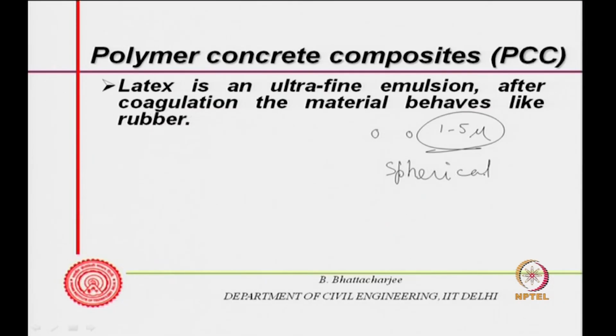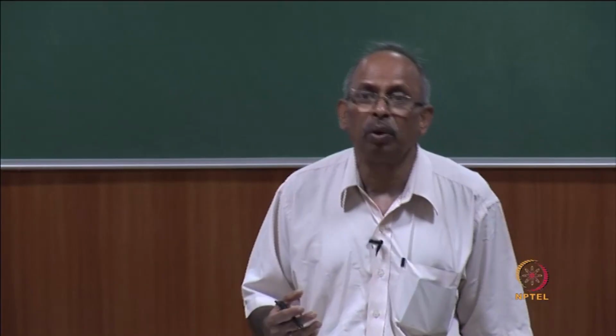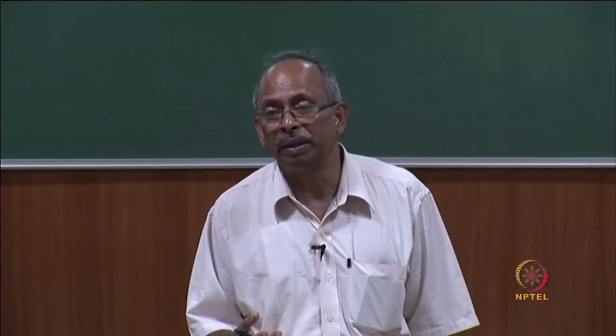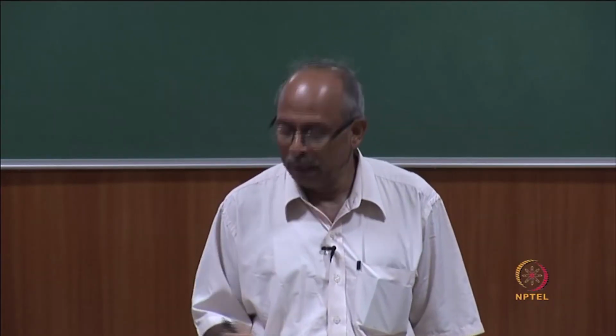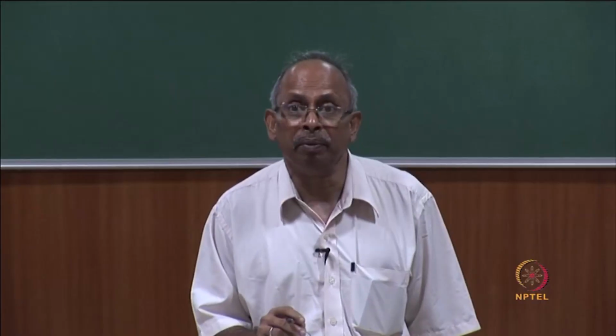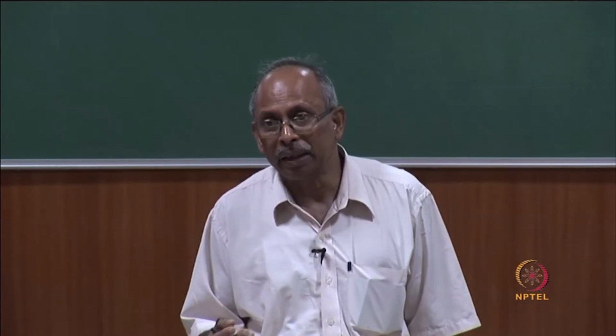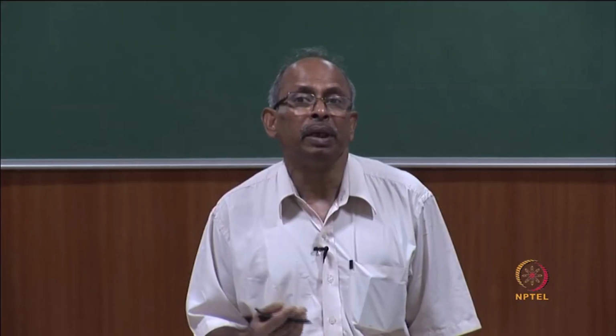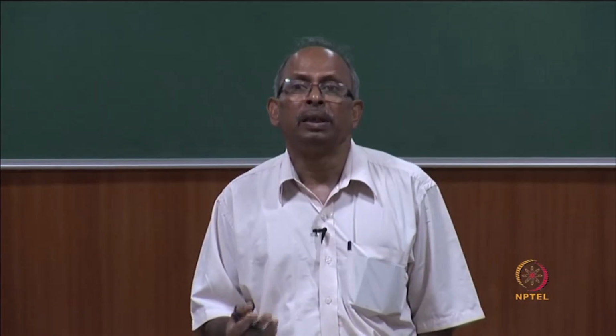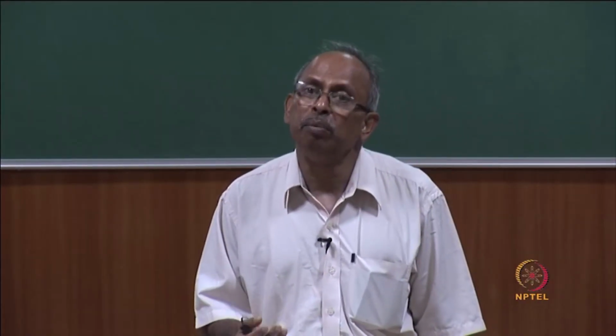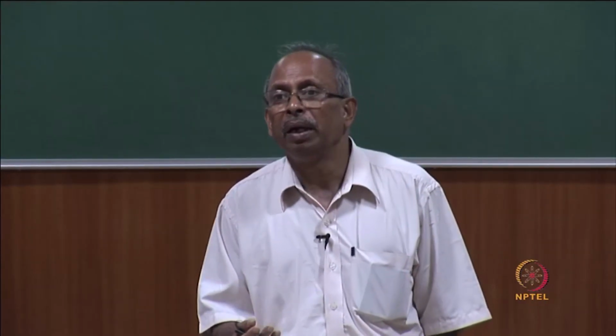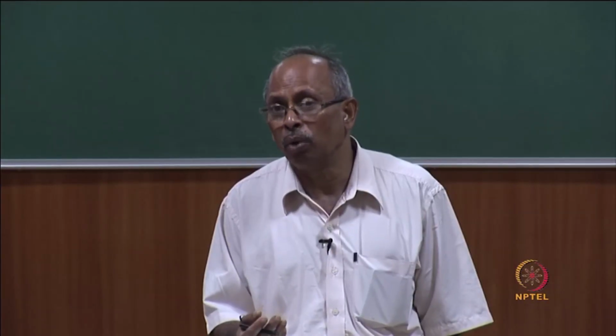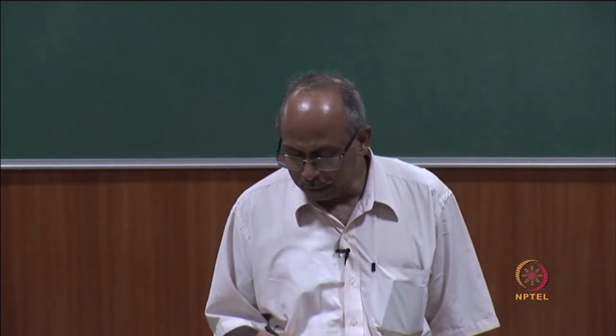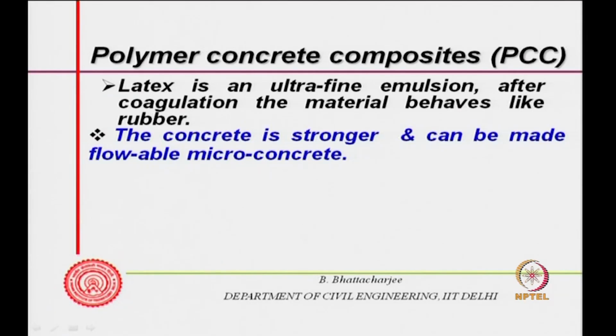This rubber latex is added to the cement concrete system, and it gets polymerized and solidified. When polymerization occurs, the molecular mass increases, and therefore it solidifies. Within the cement based system, 1 to 5 micron particles go into the interstices of the cement, and thereby increase the strength. They act as filler, then solidify and reduce porosity somewhat, and therefore increase the strength. Strength enhancement could be 1.5 times: the strength of the polymer modified concrete divided by the strength of ordinary non modified concrete of the same water cement ratio could be about 1.5 to 1.6. So, good concrete can be prepared with this, but it is costly. Therefore, it remained a repair material. One can make flowable micro concrete, which has been used extensively for repair work.